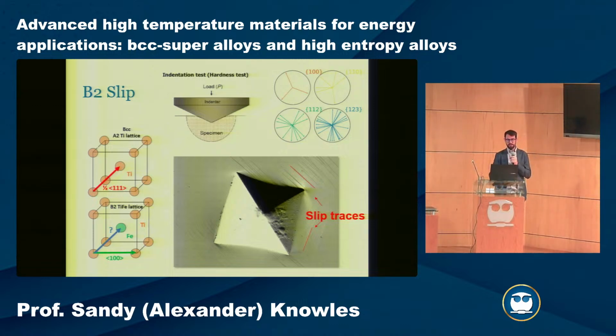In the case of titanium iron, the atoms really don't want to be dissimilarly bonded so much. They much prefer to have a titanium-iron bond than a titanium-titanium or an iron-iron bond, so it instead deforms on <100>. So you don't form an antiphase boundary, but it's a longer Burgers vector, and the challenge is then you also don't have enough slip systems for full ductility.